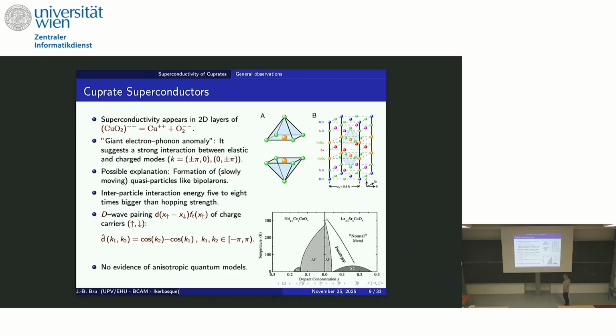One thing maybe you would be interested to know, so let's forget about what is written here, but look, for example, at this phase diagram. So how do you get a cuprate superconductor? At the beginning, you take a usual cuprate. Usually it's antiferromagnetic at low temperatures, and it's a Mott insulator. So it's not metallic. This is one famous cuprate that we have here. And at the beginning, if you are below the critical temperature, then you get an antiferromagnetic phase.